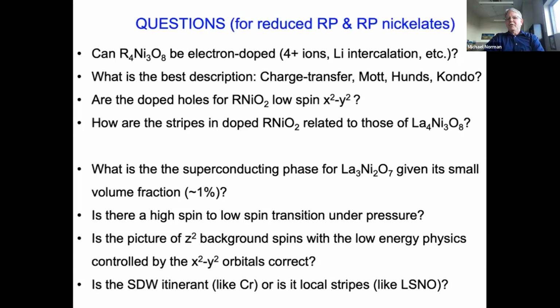Again, what's the best description? Is it charge transfer, Mott, Hund's, Kondo, some combination of the two? Are the doped holes low spin x squared minus y squared, like we expect for the cuprates? And how are the bond-centered stripes in the 112 related to the diagonal stripes that we see in the reduced 438 material?